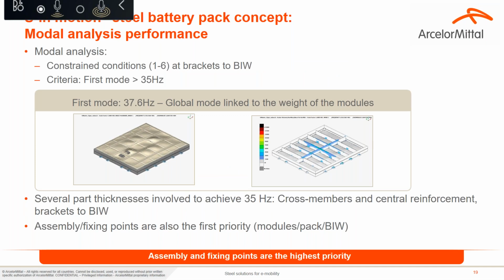Regarding modal analysis, Ricardo, our partner, gave us a good way of working by respecting at least 35 Hertz as a first mode. I remind you that there's no attachment point to the body in white in the middle of the pack. In our case, we have decided to fix the pack only with the blue part you see around the frame. This is very important. With our design, we reached 37 Hertz, so it's quite good. Of course, in this case, the material, except thickness, is not playing a role.